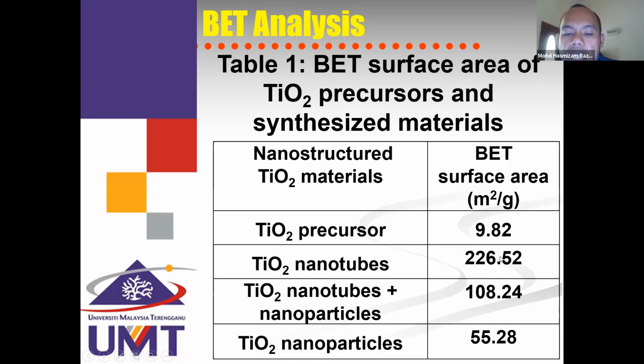As mentioned earlier, due to their hollow elongated nanotube morphology, they possess high surface area, which is more than 200 meters square per gram. For the sample of calcination at 500 degrees C, which has titanium dioxide nanotube mixed with nanoparticle, that means the nanotube is almost collapsed to produce nanoparticle. The surface area is 108.24 meters square per gram.